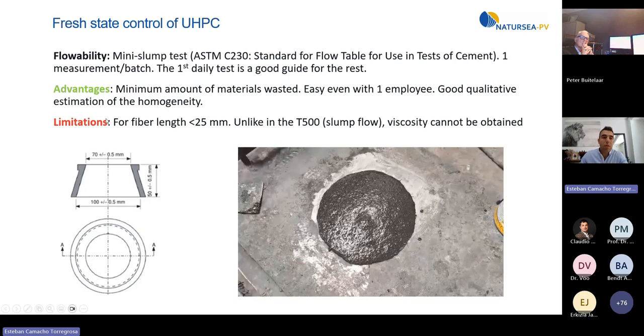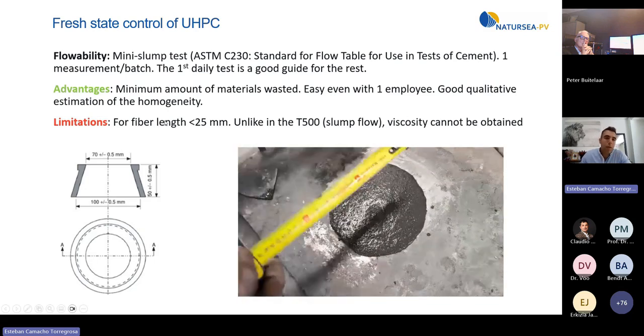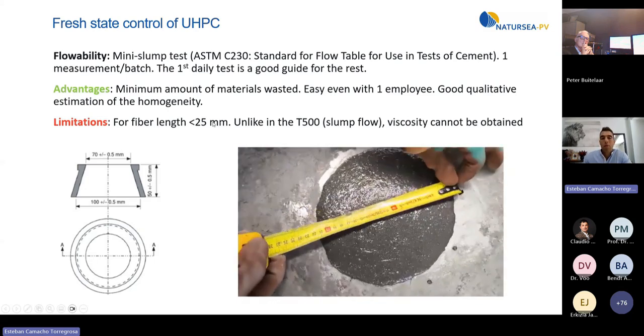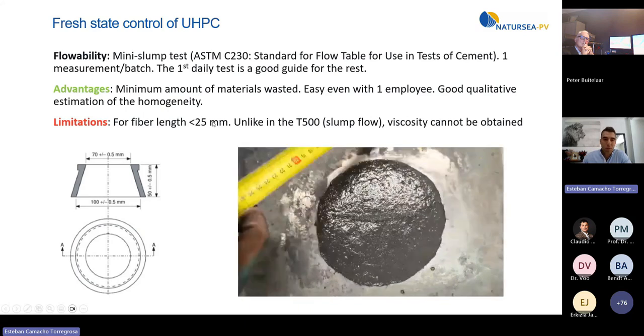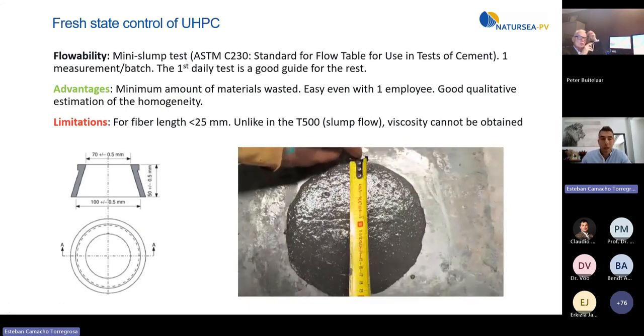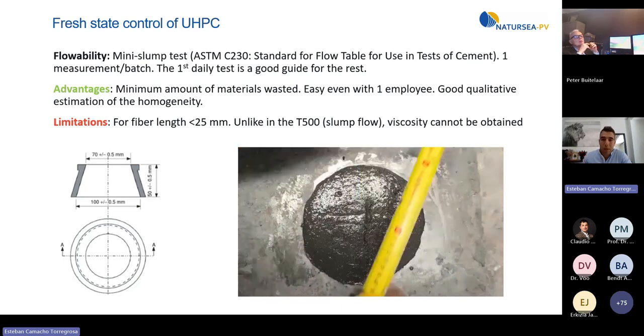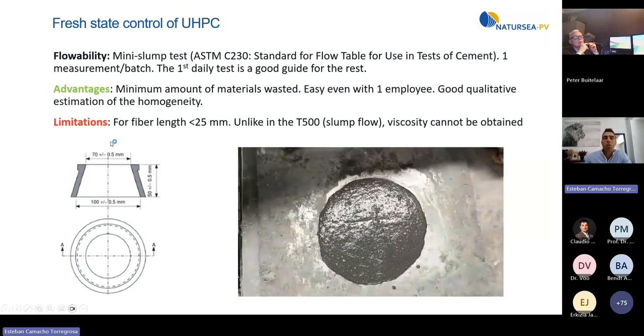What is the limitation of this test? Well, in our experience, I advise not to do it for fibers longer than 25 millimeters, because the cone has only a top diameter of 70 millimeters, and it's already difficult to introduce the material. This test provides flowability more than viscosity.